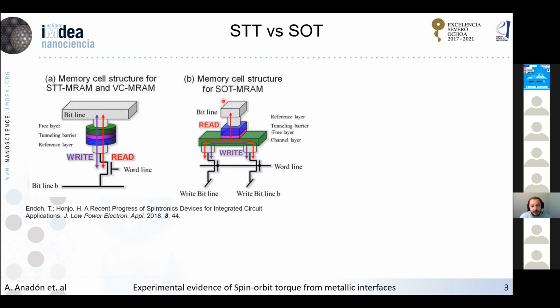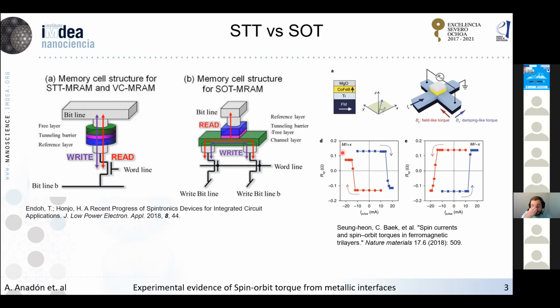the spin orbit torque. I will go into more detail in the next slide, but basically here we have a three-terminal device instead of a two-terminal one. So reading and writing go through different channels, and we are already overcoming some of the issues that we had in the spin transfer torque memories. But this does not come without limitations. To use spin orbit torque to read and write efficiently, we need to have an in-plane magnetic field, because otherwise you need a very high current to switch the magnetic layer.